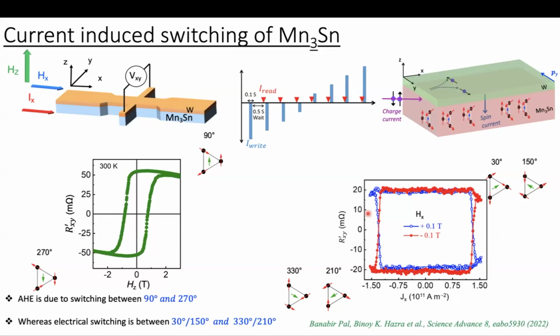Okay. Excuse me, sir, I had a query. I wanted to know, sir, is this tungsten the alpha tungsten phase or the beta tungsten phase? Again, it's a mixed phase, I would say, because the manganese 3 tin itself is a polycrystalline, textured sample. So on top of it, we could not grow beta tungsten. I was wondering if it could have been beta tungsten with a higher spin Hall angle. Here the higher spin Hall effect material is not important.